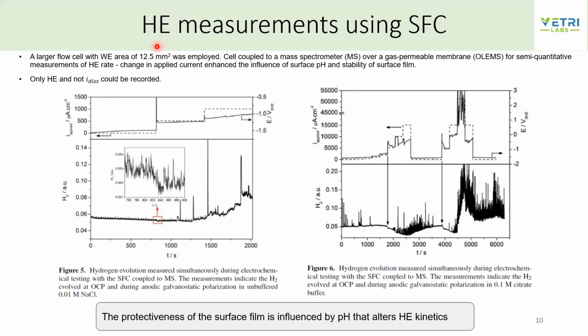Now that they have studied the Mg2+ dissolution, they wanted to study the hydrogen evolution. For this, they changed the mass spectrometer setup a little, using a different gas permeable membrane to sense the hydrogen. So now in these experiments, they were not measuring Mg2+, rather they were measuring the hydrogen evolution. This is semi-quantitative, meaning they're not able to study the exact amount of hydrogen evolving in a quantitative measure.